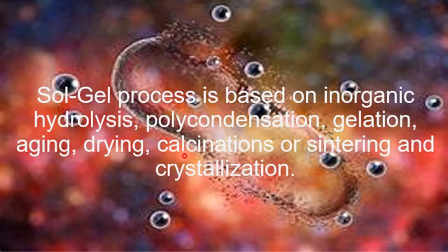Please note, student, that different materials have different calcination temperatures. If we want to prepare ferrites from the sol gel process, the calcination or sintering temperature for ferrite is around 850 degrees centigrade. So at that temperature, the solution, which is in the form of a dried solid, is converted into a single phase ferrite.